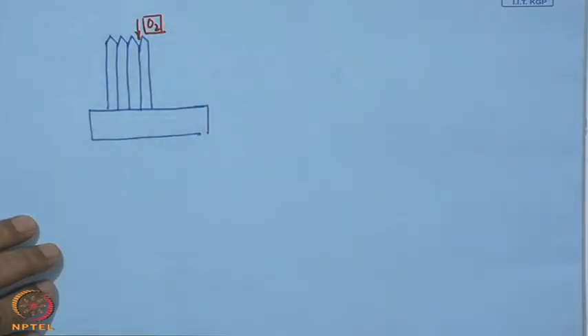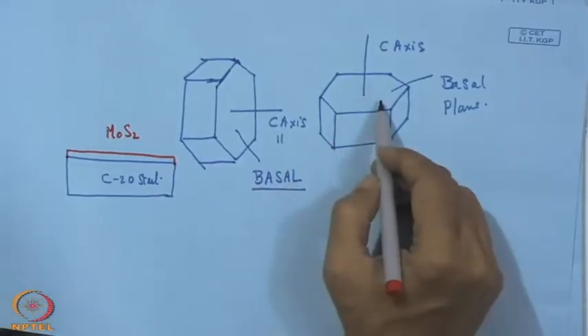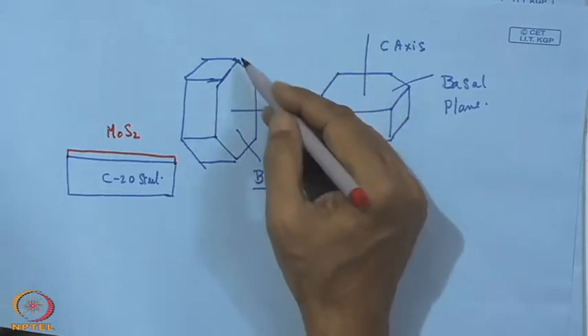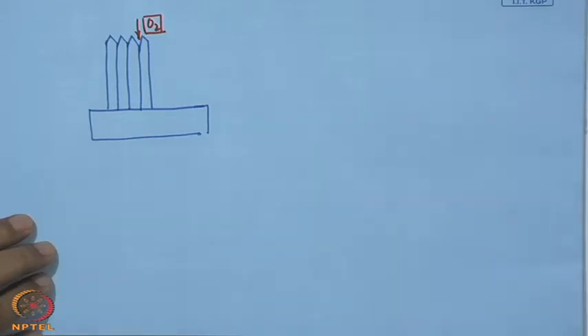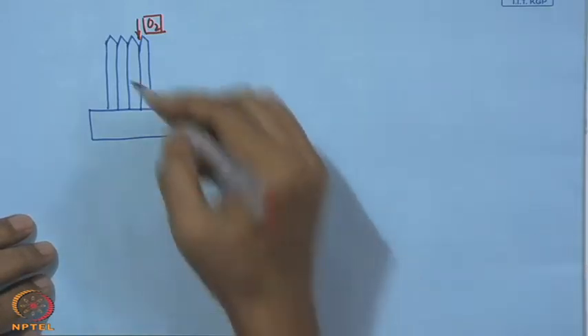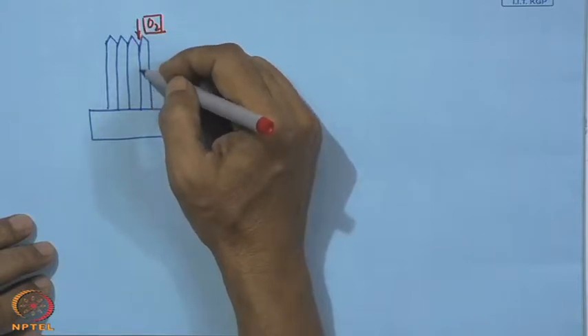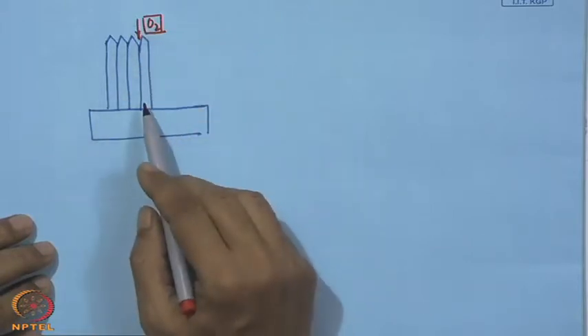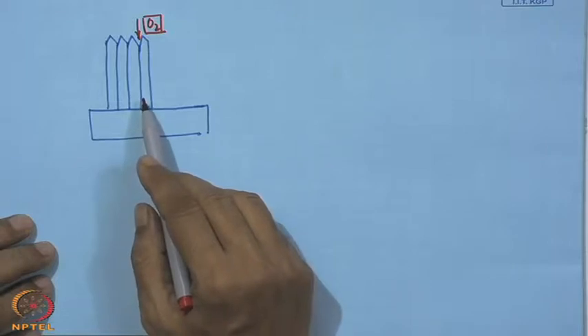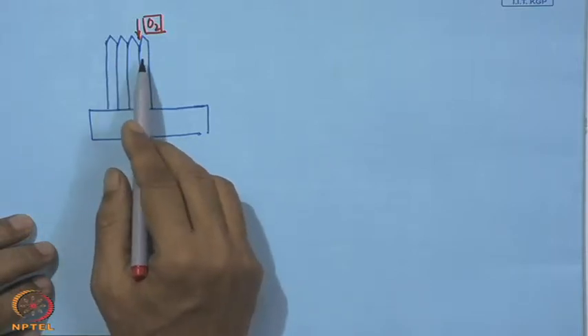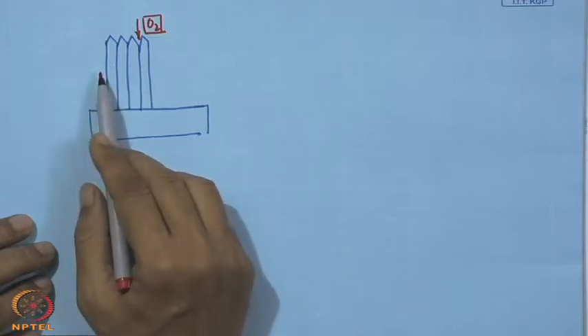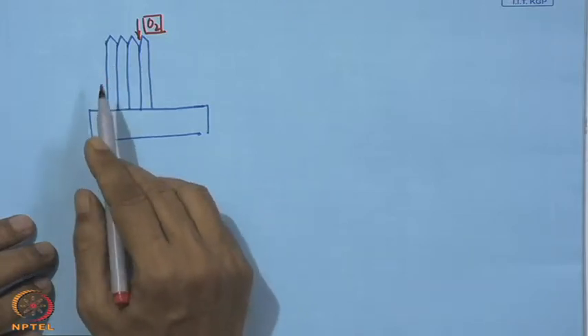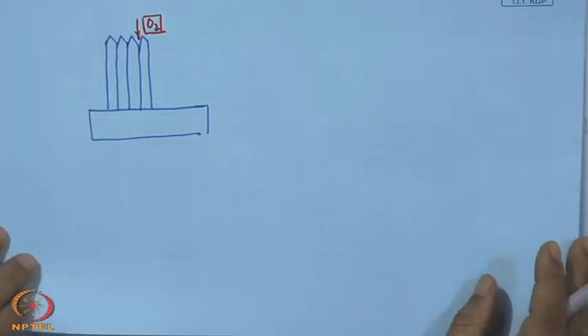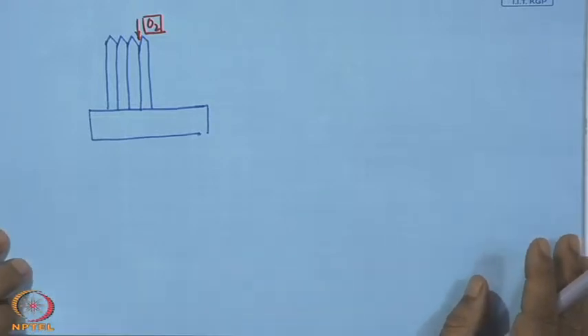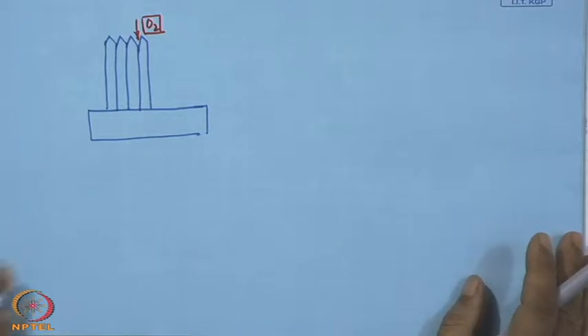That means, here the attack will be difficult, but here the attack will be rather easy, and in this way the atmospheric oxygen, or in a humid atmosphere the moisture, can get in, and then it may cause deterioration of the quality of the coating. So, under the action of this force this coating will immediately break, and that will lead to a high value of friction. So, this is what we call the basal plane and edge plane.